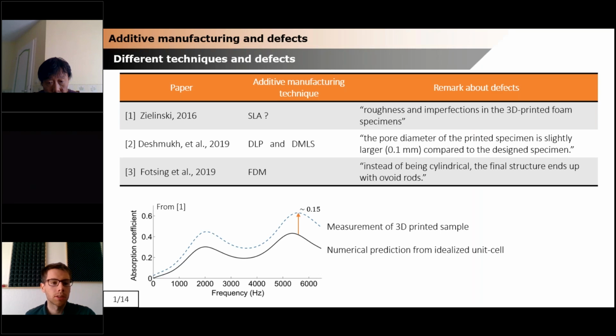So let's start with the defects coming from additive manufacturing. From what we see in the literature and also from what was discussed this morning, for a lot, I would even say for all additive manufacturing techniques, say SLA, DLP, FDM, and so on, when you print a porous material, the material you obtain is not the one that you had in mind when starting your project. For instance, from this paper, it is said that there are roughness and imperfections on the foam that is printed. Second paper, the pore diameter is not exactly the one that was expected. And third paper, the filaments are not cylindrical as expected, but end up being ovoid.